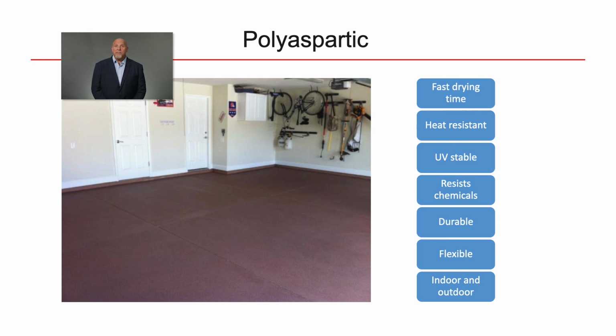Polyaspartic coatings offer several benefits such as UV stability, resistance to abrasion and impact, and resistance to harsh chemicals including salt, motor oil, gasoline, MEK, and acetone. In some applications, polyaspartics are applied over epoxies to increase the chemical resistance of the epoxy. Polyaspartic coatings can be applied in a wide range of temperatures, from -20 to 130 degrees Fahrenheit, and will not melt when exposed to high heat up to 350 degrees Fahrenheit.